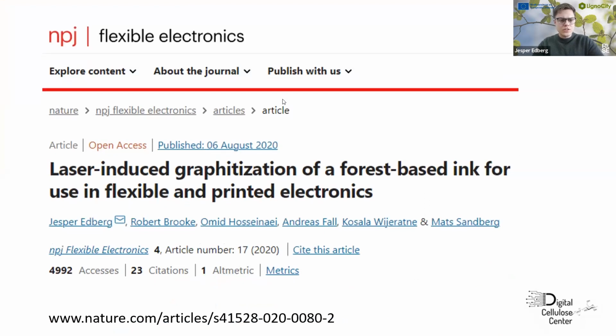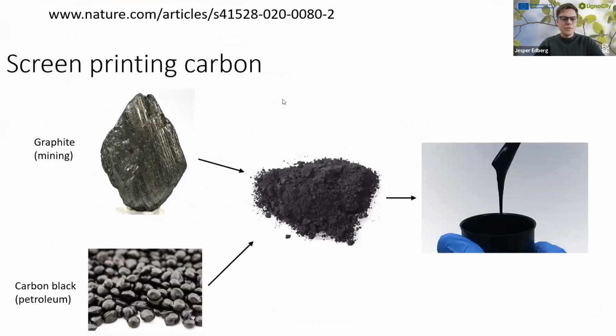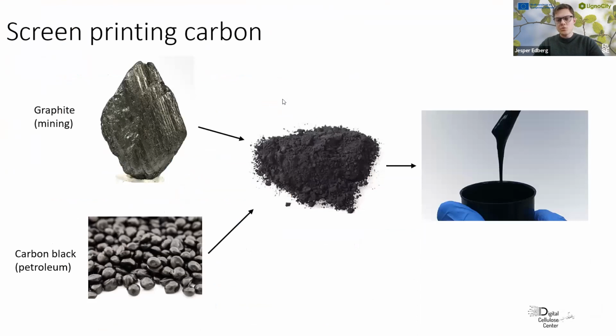So we published this research a couple of years ago. It's a paper called Laser-Induced Graphitization of a Forest-Based Ink for Use in Flexible and Printed Electronics. And this is also why I mentioned a little bit about printed electronics, because in printed electronics, we often use carbon-based inks to make these printed devices. But the carbon in these inks is made from a mixture of graphite and carbon black, which comes from mining and oil, so they're not very sustainable.